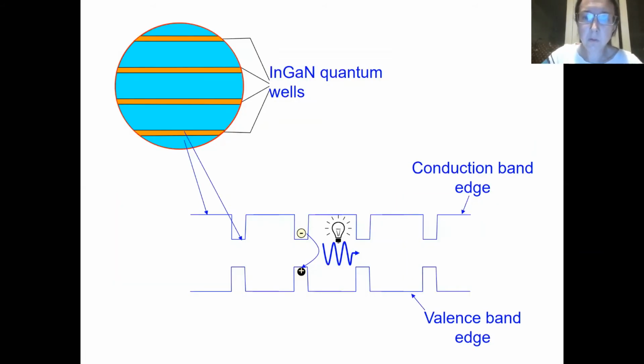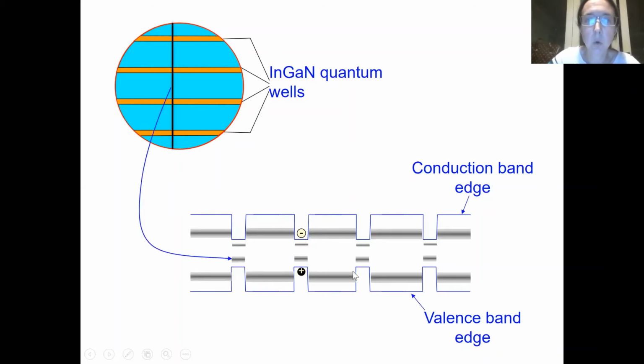So we've already said that what we want is to trap the electron and hole in these thin layers, these quantum wells, and have them combine with one another and give out light. What happens if we introduce one of these defects running all the way through the quantum wells? So when I showed the pictures before, say the TEM images of the real dislocations, we were showing them as an extra half plane, and then we saw the disordered rings of atoms. But that disorder runs in a line into the crystal, into the page. And this line I'm showing here is that line of disorder, okay, that would run all the way through the crystal from that dislocation.